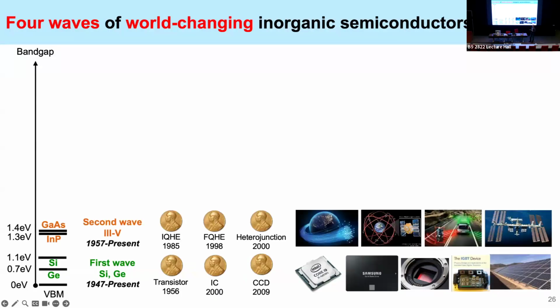The second wave is the 3-5 semiconductors, right? So they have a slightly larger band gap compared to silicon and germanium. However, the big difference lies in that they have a direct band gap. So this means that they can be made into very efficient lasers, LEDs, and photodetectors, and they have become the backbone of the global internet today. In addition, the electrons and holes can move very fast in those 3-5 semiconductors, right? And therefore, today, the world's fastest electronic devices are also based on 3-5 semiconductors. And there have been 3 Nobel Prizes related to 3-5 semiconductors: 2 for the quantum Hall effect, and 1 for the heterojunction.